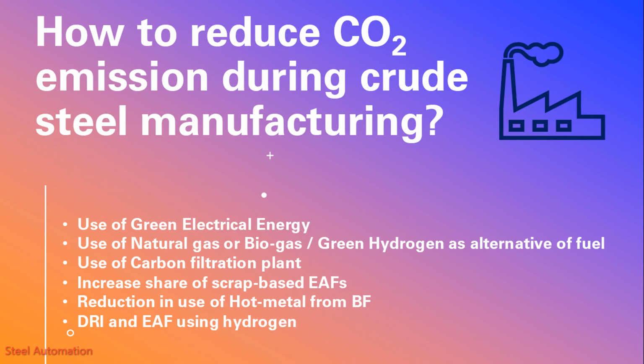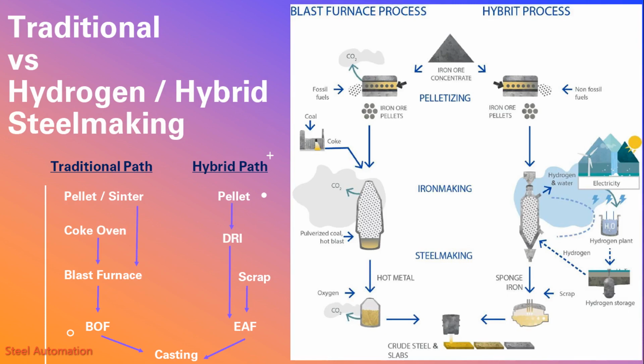We can see from the process flow diagram that in conventional iron production, blast furnaces use coke, nearly pure carbon coal, to heat ore and separate oxygen from the iron in the ore. For this step, HYBRIT uses a different, more efficient process called direct reduction. While this can be done with natural gas, or even coal, as the agent that removes the oxygen, HYBRIT's innovation is to use hydrogen, made from electrolysis powered by renewable energy. Instead of soot from unburned carbon and large amounts of CO2, the HYBRIT plant emits clouds of water vapor.